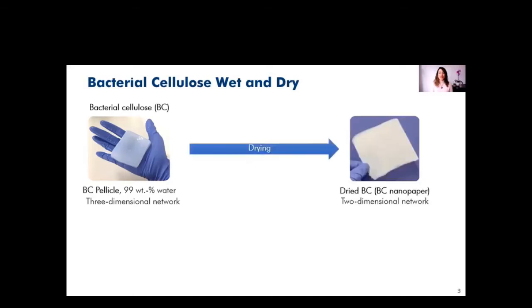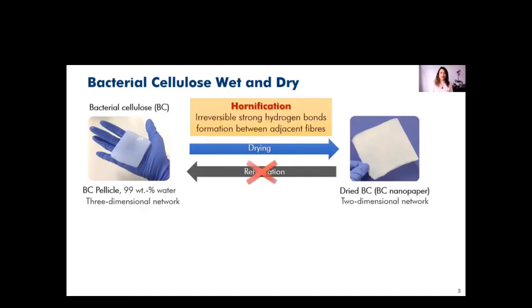This BC pellicle, when it's dry, is formed as BC nanopaper that is a two-dimensional network. The question is, can we reverse this process and rehydrate the dry BC? And the answer is no, because there is a process that is called hornification, that when you dry cellulose, there is a formation of irreversible strong hydrogen bonds between the adjacent fibers. And due to this hornification process, the BC nanopaper presents high mechanical performance with a modulus of 20 gigapascals, a tensile strength of 188 megapascals, and with a strain of 1.4%.